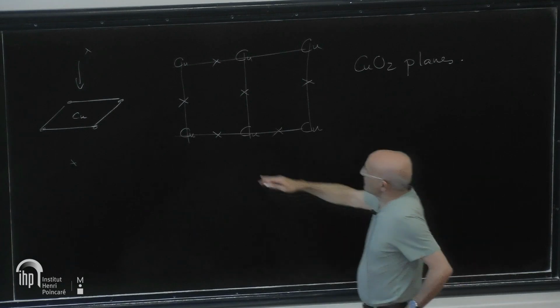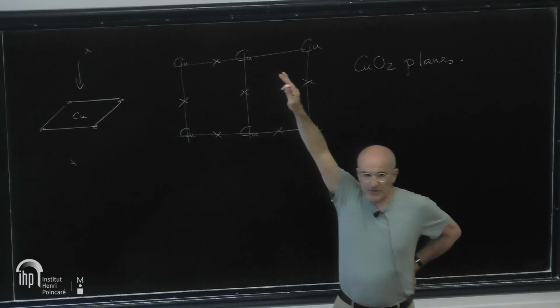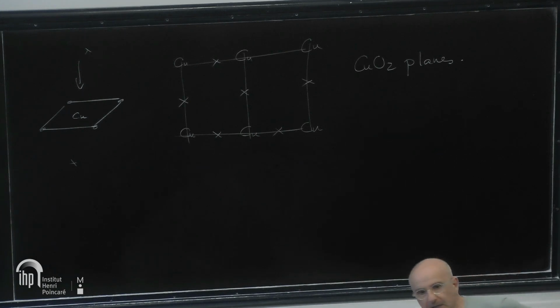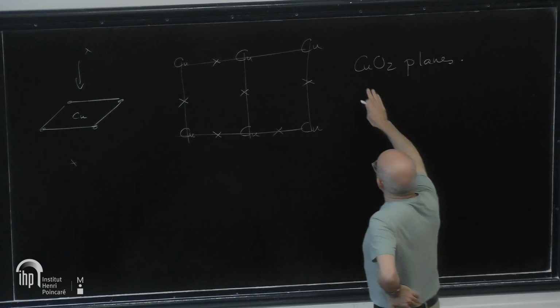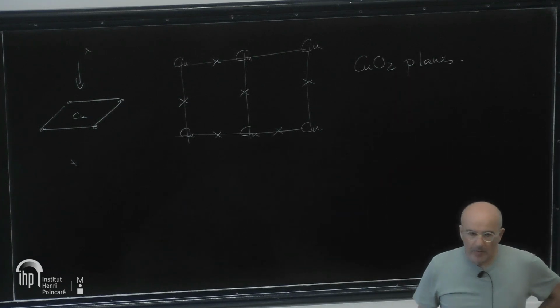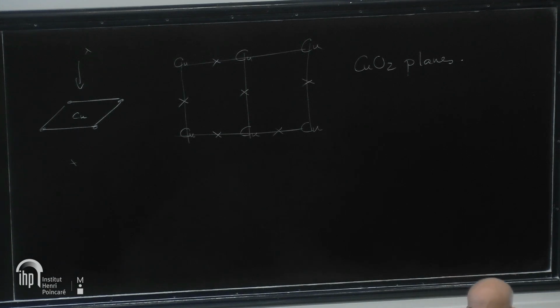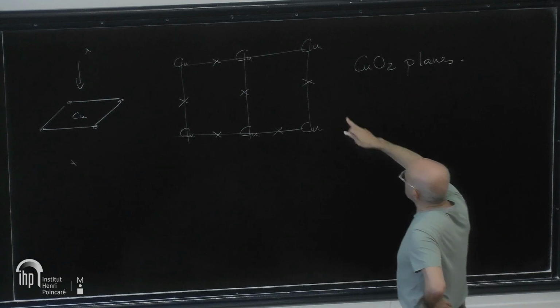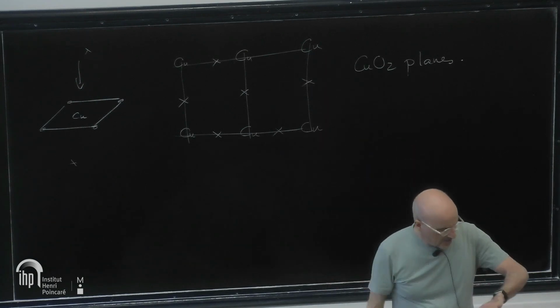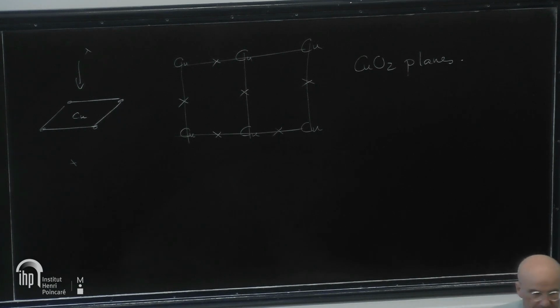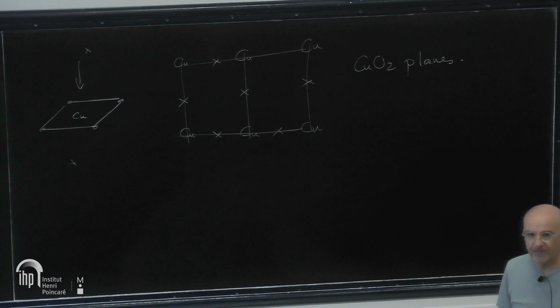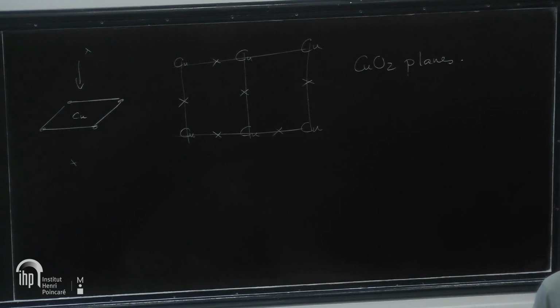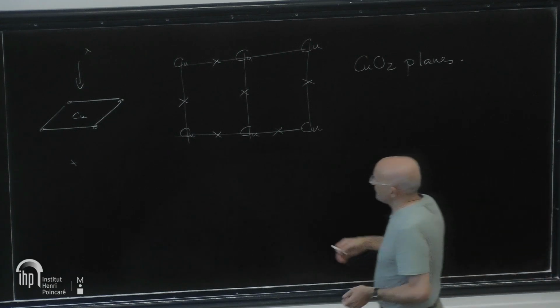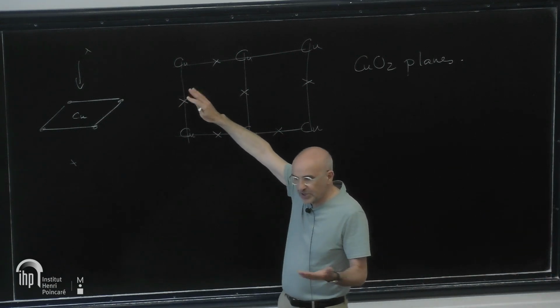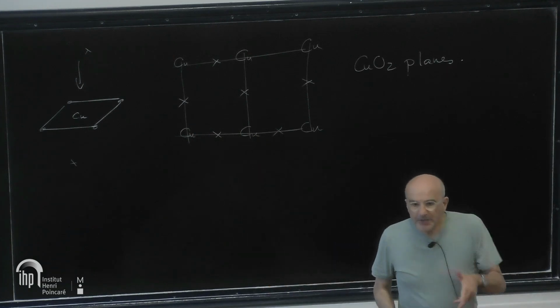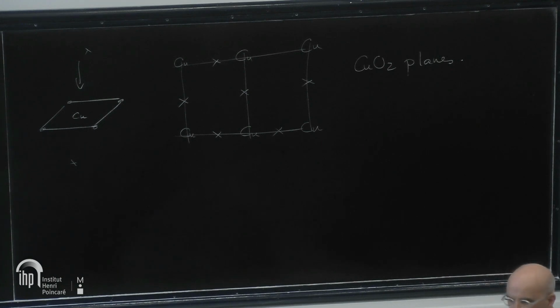Now, you could ask, well, but why does that have anything to do with a simple model like the Hubbard model that I described before? Because obviously, even though I've simplified tremendously the problem to just one copper-oxygen plane, this plane contains many atoms, hence many orbitals. Each copper atom, the active shell is the 3d shell of the copper atom, hence it has 5 d orbitals plus spin, which is 10 quantum states. 5 because L is equal to 2, and 2L plus 1 is hence 5. Okay? And the oxygens have at least a partially filled 2p shell, hence it has at least 2 orbitals in the plane, px and py, which are relevant to the problem.